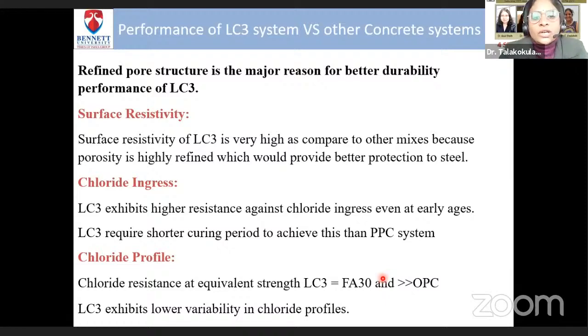The refined pore structure is very good for LC3 concrete, and this is the reason for its better durability performance than the OPC and also the fly ash blended concretes. The surface resistivity is very high as compared to other mixes because porosity is highly refined, which would protect the steel better. For chloride ingress, it has the highest resistance even at early stages, and the LC3 system requires a shorter curing period than the Portland pozzolanic systems.